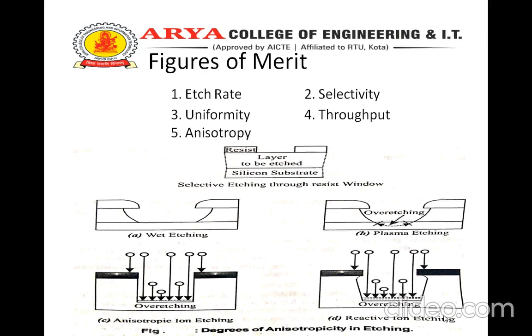Next is throughput. An important aspect to remember is the concept of throughput, which is a measure of the time it takes to process a lot of wafers. Batch processes are those in which an entire lot of wafers is processed together; obviously, throughput in such cases is very high. Examples of such processes are diffusion and wet etching. Single wafer processes are those where the process is done essentially one wafer at a time, such as mask alignment. Obviously, the throughput is much lower in this case. Plasma-based processes fall in this category.